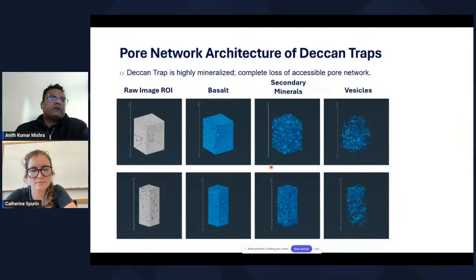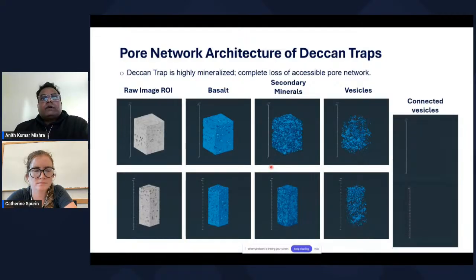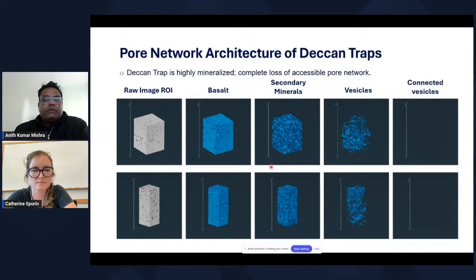We have collected a total of 20 samples or so. But I'm not going to share all of it here because of the time constraint. But when we tried to see the connectivity in the vesicle network, we found nothing. So there is no connectivity present at the core scale for these basalt samples.